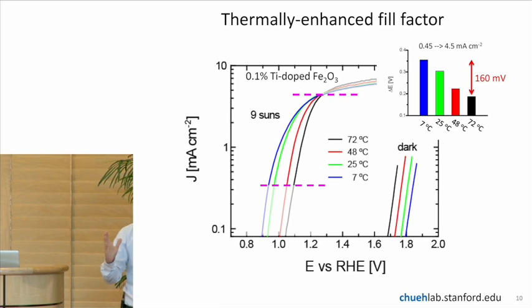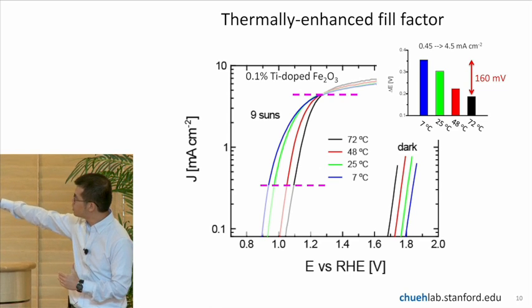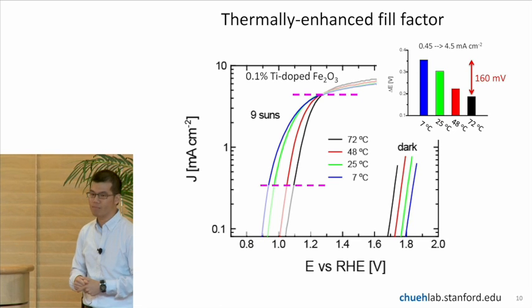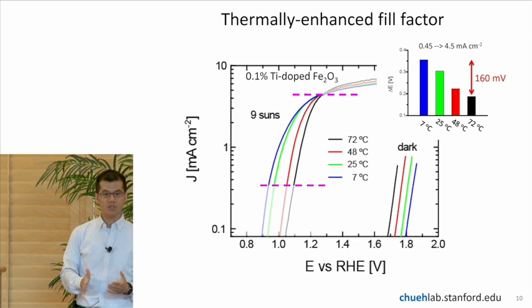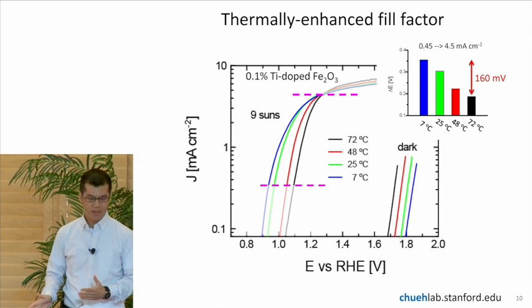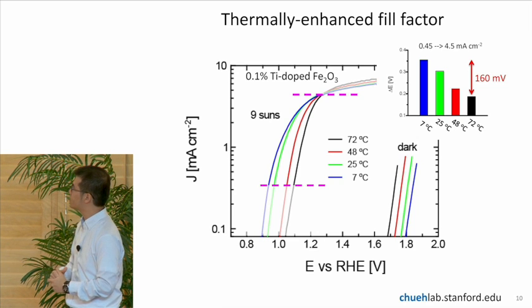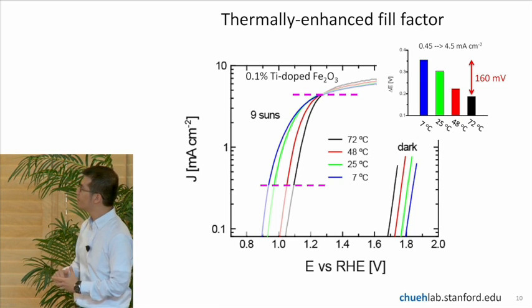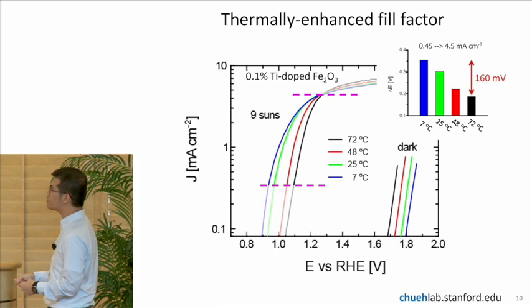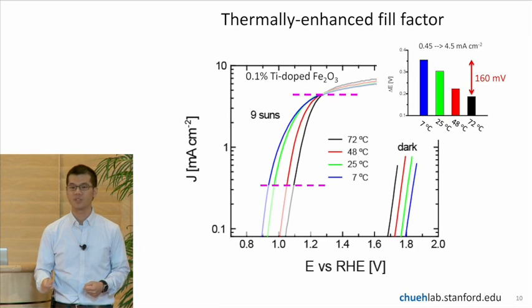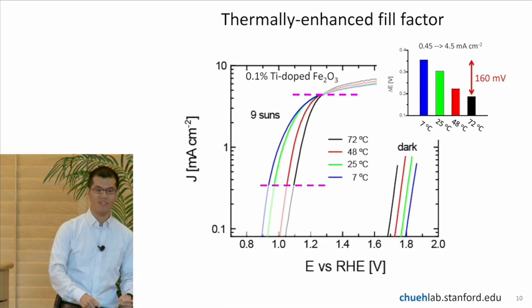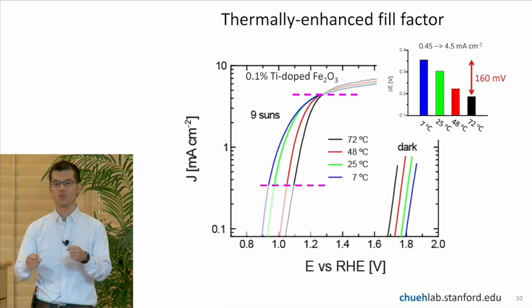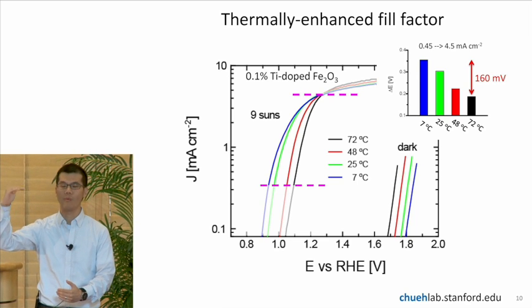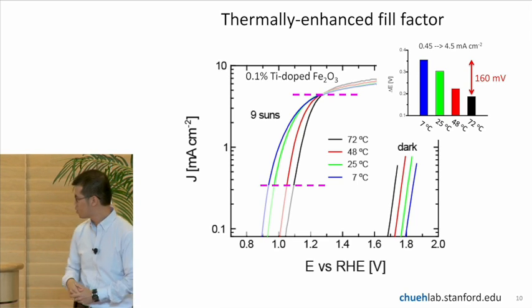So if you just focus on the range between 0.3 and 3 milliamp per square centimeter, you can actually see the curvature changing. So when the temperature is low at 7 degrees Celsius, it's quite a bit curved. And when you increase the temperature to 72 degrees Celsius, the curvature decreases substantially. So this means that the amount of excess voltage you need to get to the high current you want is now less. So let me plot that.